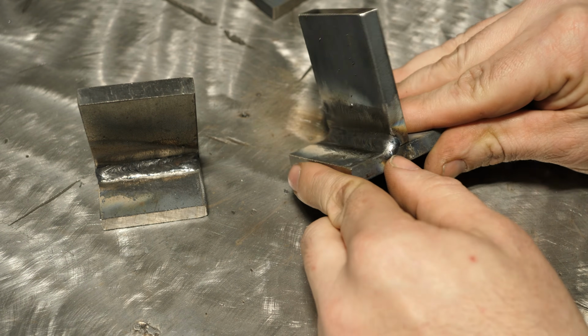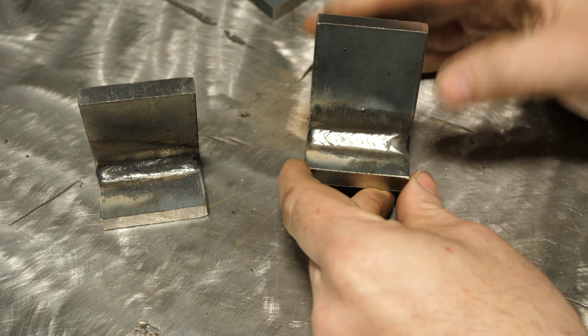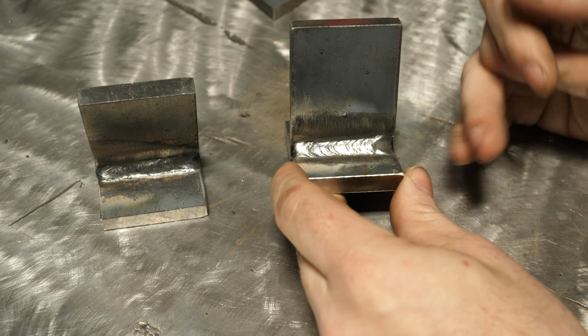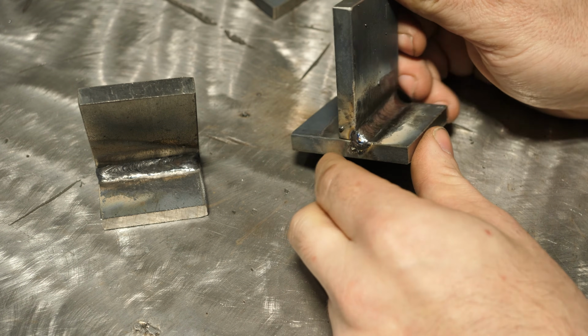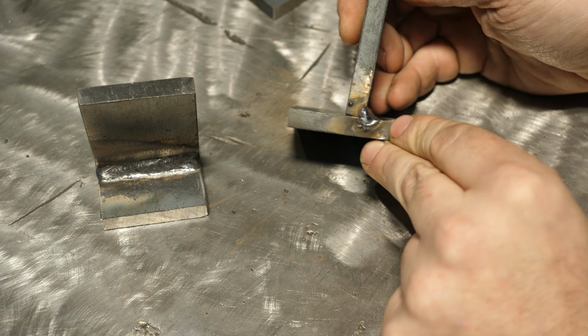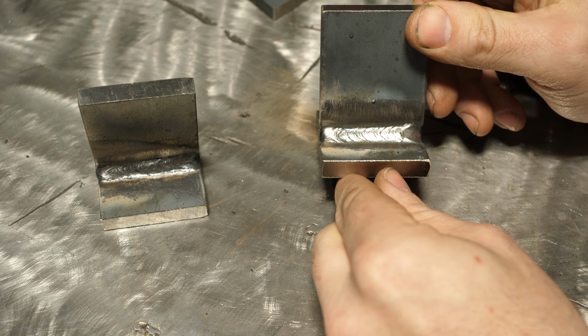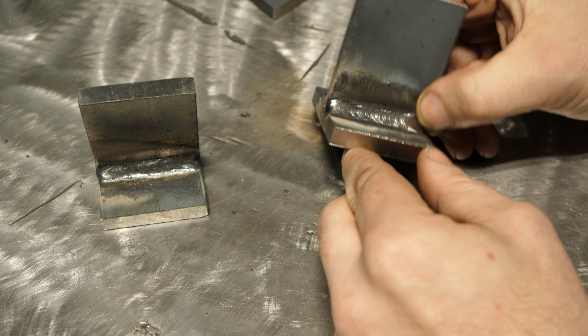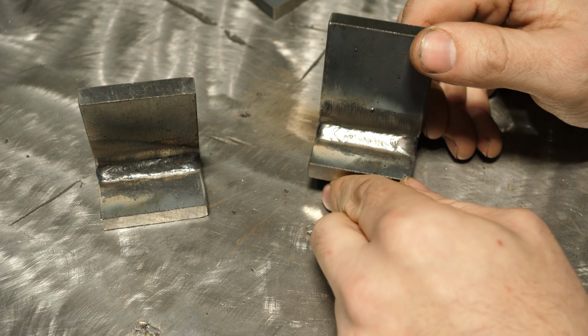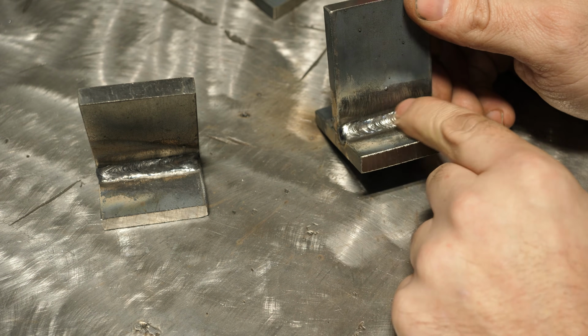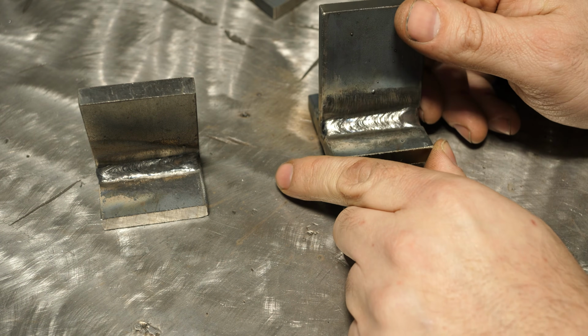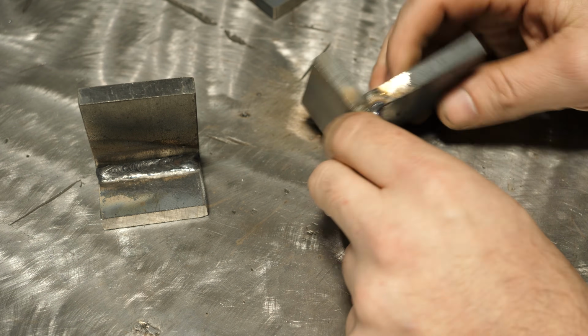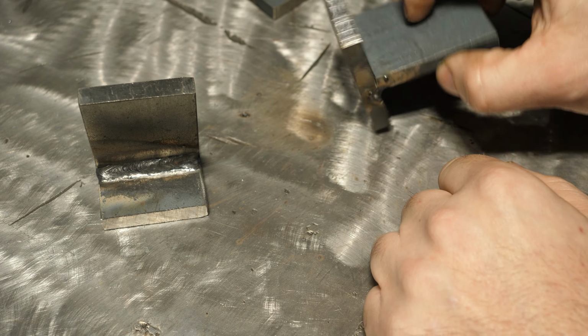This guy, which is basically perfect, the corner isn't too blown out. It has a little bit of a divot there, but it's not any different than any other test I've done, so I don't really see that as a negative. The start's nice and hot. It wrapped the corner pretty good. Very shiny weld, very acceptable. There is not one hint of undercut or any other weld defect in the meat of that, so that all looks good. This we are going to press in the shop press and try and flatten out and see if it passes.